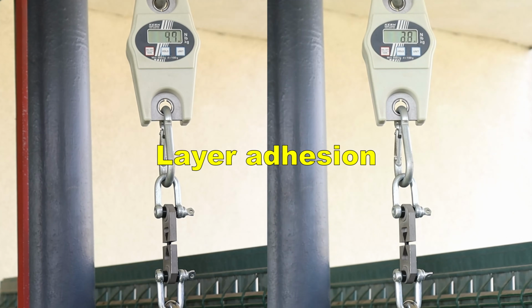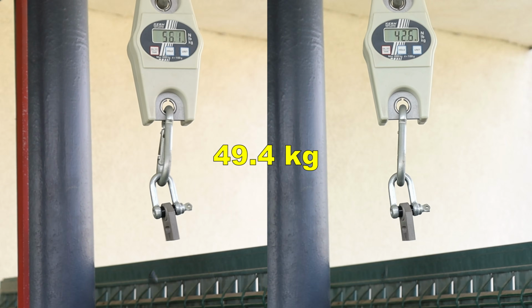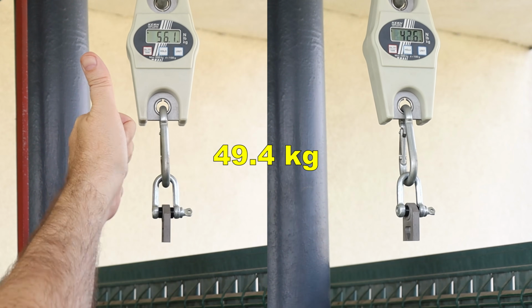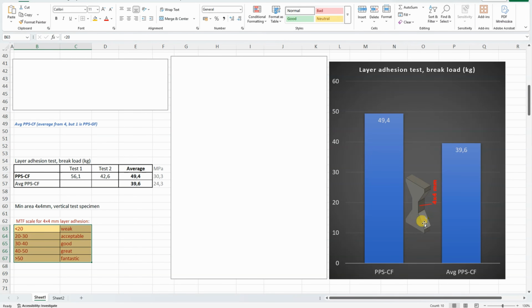And now layer adhesion, vertically printed. My rating for this size of the test object, and according to the table, this PPS-CF has a great, almost fantastic layer adhesion, much bigger compared to the average PPS-CF.